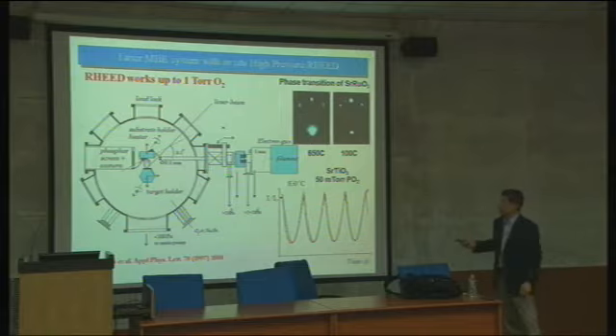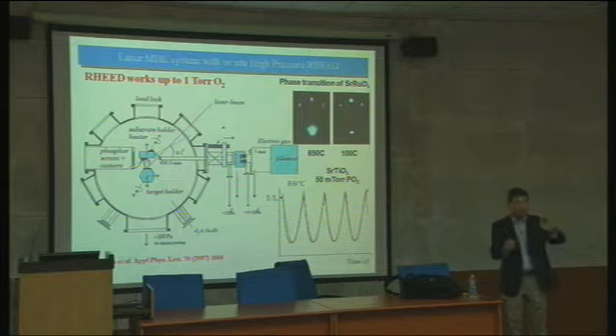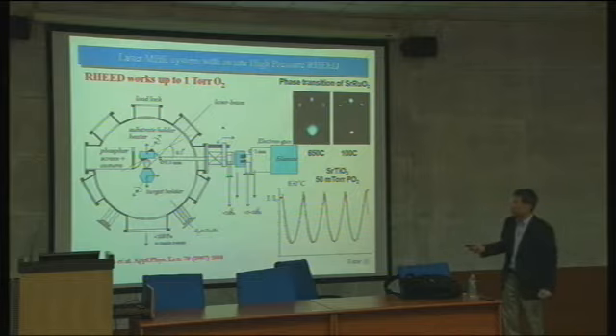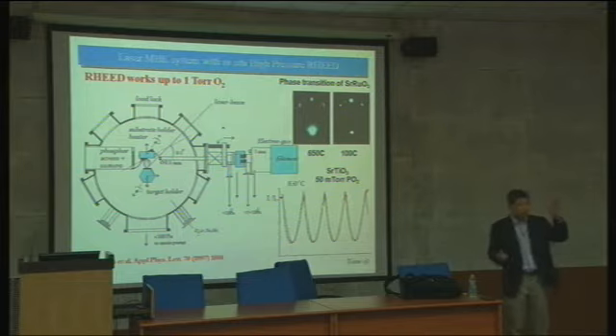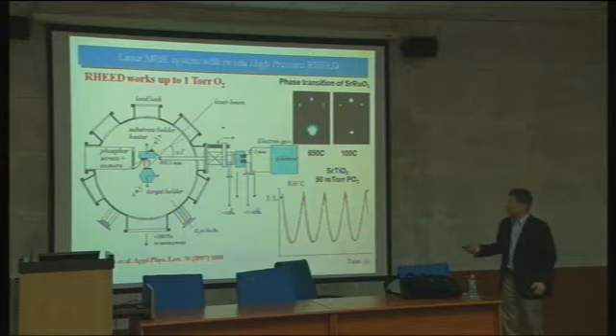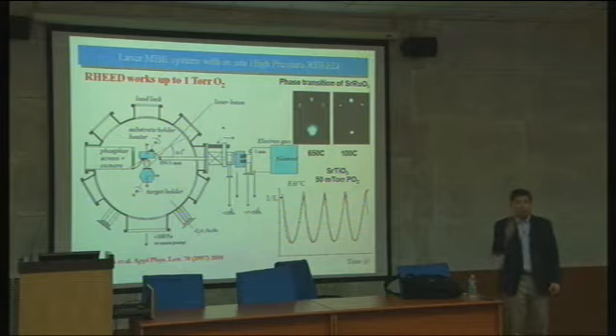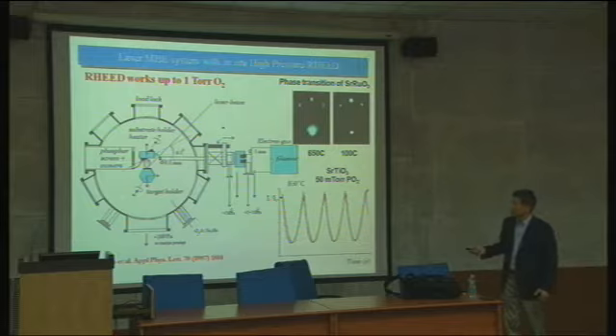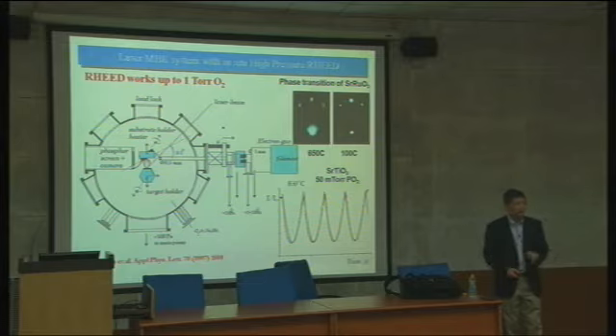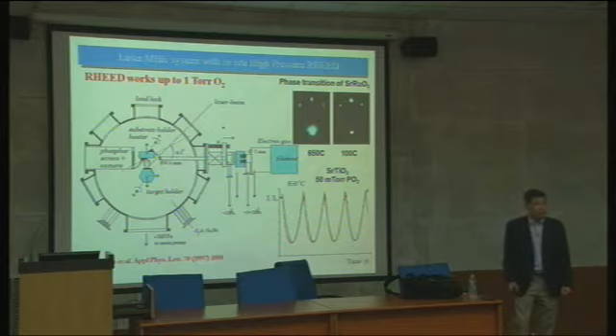So in order to do that, basically two things. One is that the axis of the electron beam is very, very close to the sample. And the phosphor screen for imaging the RHEED pattern is pushed into the chamber. The distance from here to here and from here to here is only a few centimeters, very, very close. But the exit of the electron beam, the hole diameter, is a few hundred microns. Very, very tiny holes, and then you have differential pumping.